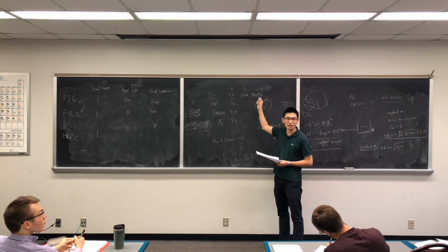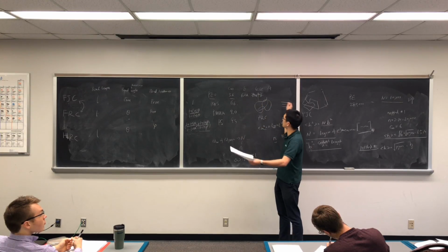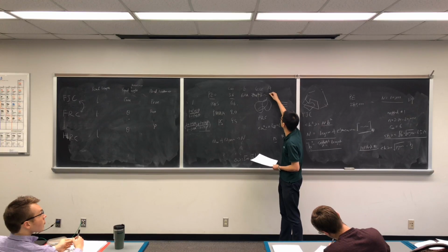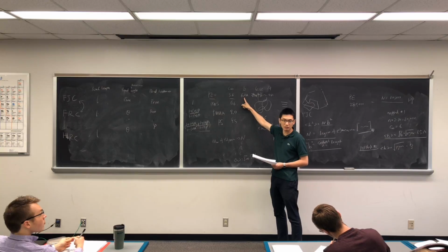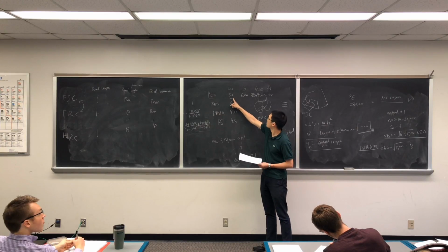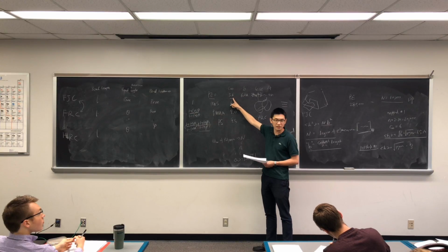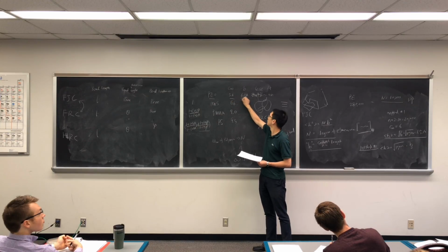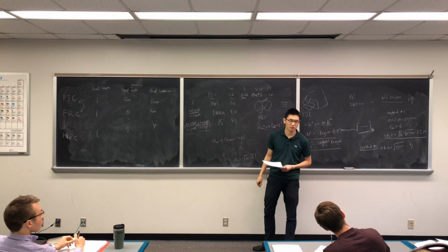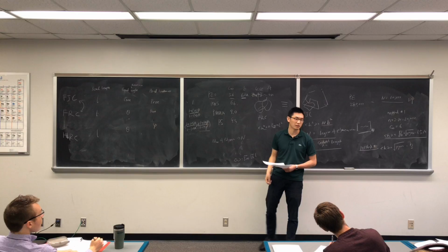The CO bond is slightly longer. But if you add everything straight, this will be somewhere close to 4.5 angstrom. But since we use a hypothetical B, it's considering this C infinity or characteristic ratio. You can directly use this to calculate. NB squared would be easier to use.